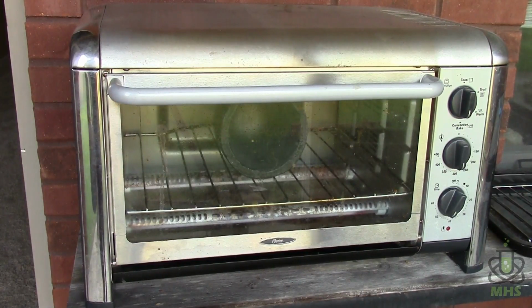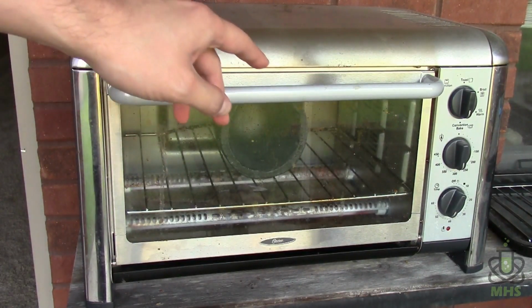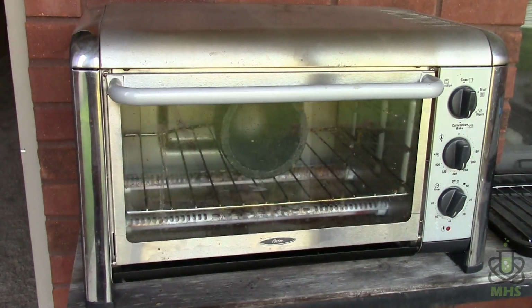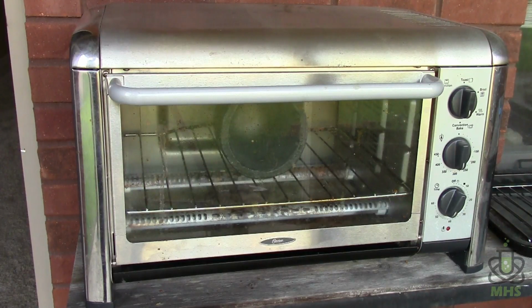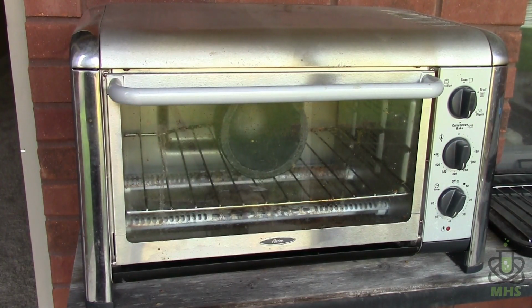So the way to do that is we first heat it up in this old toaster oven that I have, and I've got it on 300 degrees for about an hour. And I think I'm actually going to crank it up to 400 in a minute and let it run for the full hour at 400, because I believe 400 is the correct temperature. But anyways, this slow heating part is just to drive off any absorbed moisture. And once it's hot, then we'll put it into the furnace and actually crank it up to red heat, and that'll really drive off all the moisture, and then it'll be correctly tempered for use.